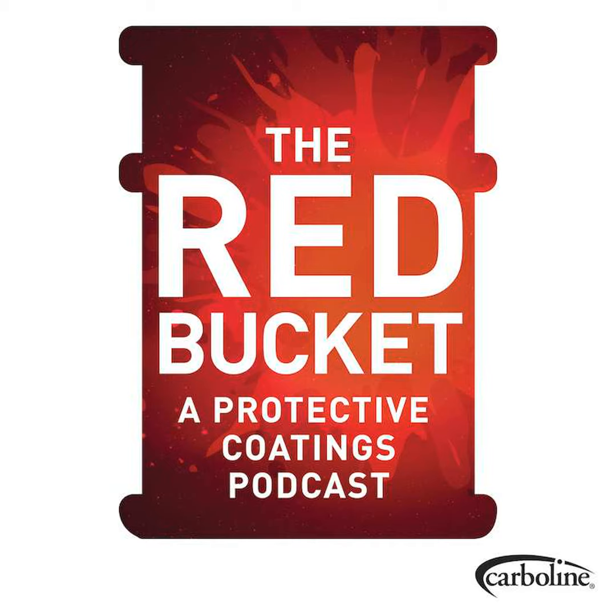And that work is particularly violent with dry sulfur, right? Because sulfur itself, the word you've used when we talked about it in the past was how tenaciously it sticks to itself and to any other surface. Yeah, and that's part of it: if it actually freezes and turns from a molten state to a solid state, wherever it's in contact with the car or the lining, it can tenaciously cling or adhere to the lining itself. And then the same problem can occur, either from the weight of the sulfur itself or from it physically being removed during the unloading process by someone cleaning it, perhaps.